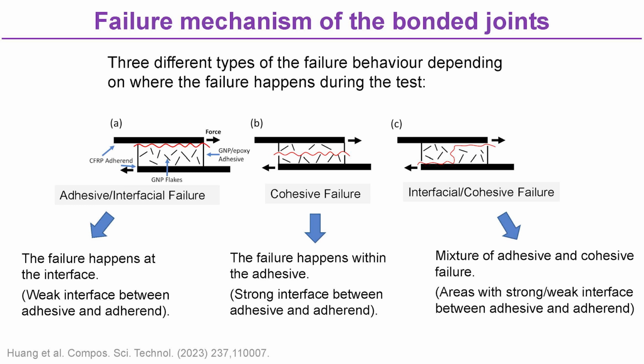Of course, we wanted to investigate the failure mechanism of the bonded joints. For us, it is very important to understand and to know what's happening during failure so that we can decide which direction to take in order to keep improving the mechanical properties of these repaired samples. There are three different types of failure behavior depending on where the failure happens during the test. The first one is the adhesive or interfacial failure mechanism, where the failure happens here at the interface between adhesive and adherent, and it is typically associated with a relatively weak interface between these two components.